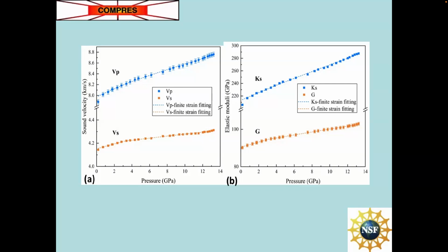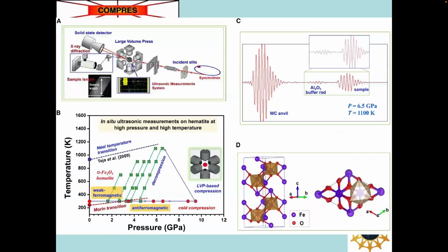Now, hematite's a strange animal, so you have to be careful when you measure it. That's revealed by a recent paper published in iScience by Yongtao Zhou, former postdoc at Stony Brook, working with Baosheng, but in China now. Next slide, please. And this is his apparatus. Again, it looks like a DIA-type configuration with a synchrotron X-ray generated here and the diffraction detected by the solid-state detector. The ultrasonic measurement system, in a different direction, measures the acoustic travel times of both P and S waves, and they can be measured as a function of pressure.